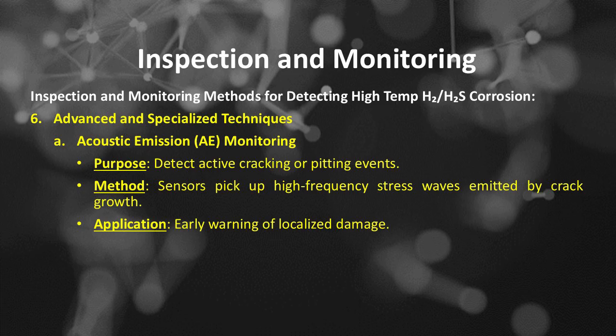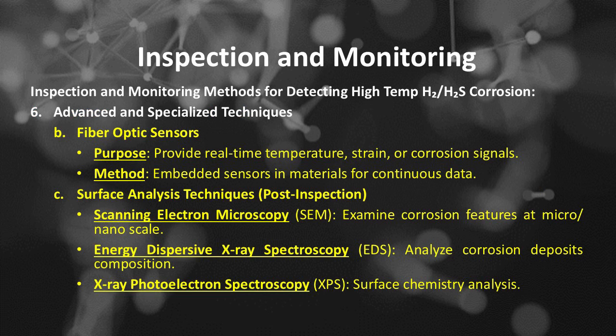Inspection and monitoring methods. Number 6 is advanced and specialized techniques, which includes: Number A, using acoustic emission monitoring. This is purposed to detect active cracking or pitting events. The method is sensors picking up high-frequency stress waves emitted by crack growth. The application is for early warning of localized damage. Number B is using fiber optic sensors. This is purposed to provide real-time temperature, strain, or corrosion signals.